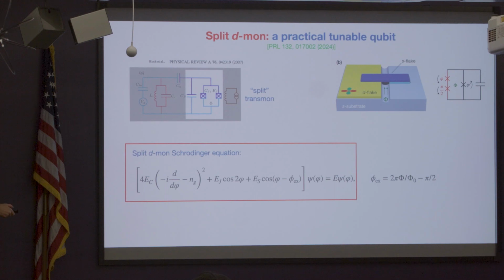Josephson energy. In the case of this split d-mon construction, it gives us an additional term in the transmon equation. So these first two terms were there originally, and what this additional structure gives us is an additional term here, which has a cosine phi structure minus some external flux that we can tune by hand. Okay, and so this design is similar to what is being used for conventional transmons. This is a more realistic variant of what people would use. So what we're solving, and what Rishi has solved, and I will show you the result of, is this particular equation where this extra term can be controlled by the amount of flux that we put through that hole.